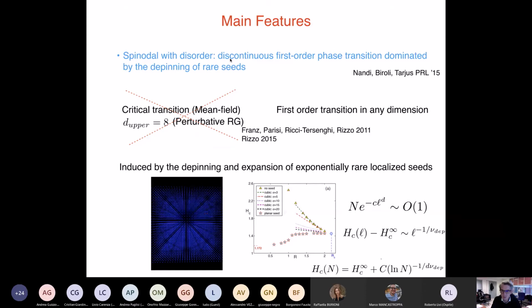Now, we want to understand what this transition is, at zero temperature, in the case of the random field Ising model. Naively, first it's a spinodal: you just follow one state, and then the state becomes unstable. It's a spinodal in the presence of disorder. Spinodal transitions at finite temperature in principle do not exist. It's a similar argument to the yielding transition, because you nucleate the other phase before approaching the critical point related to the spinodal transition. But if you're at zero temperature, you could think that it exists.